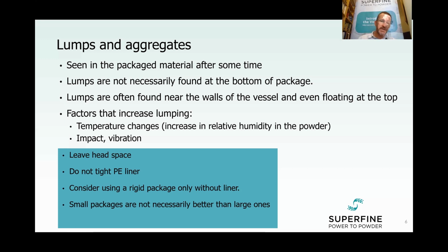So the tips I can give you for packaging are, first of all, I would advise to leave some headspace and not to tie the polyethylene liner tightly because it creates a lot of pressure on the powder, especially if you have severe aggregation. We had one case, a very extreme case, I remember, that we had a powder that was shipped in very, very small containers, only like 1 kilogram container. But this 1 kilogram was turning into solid.